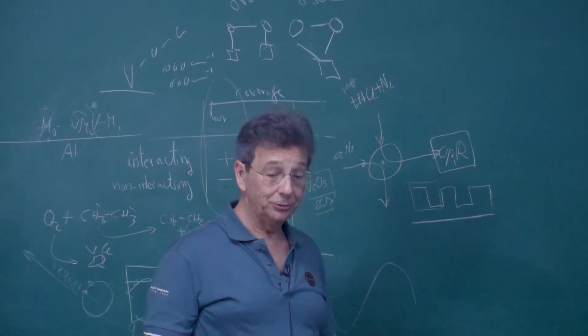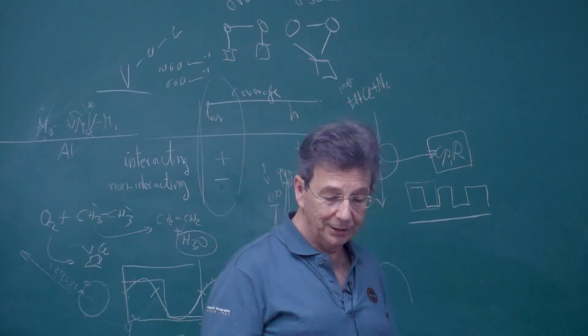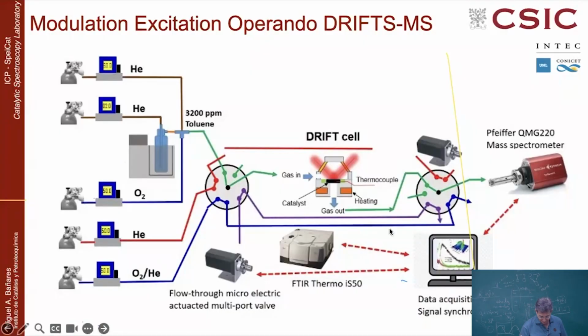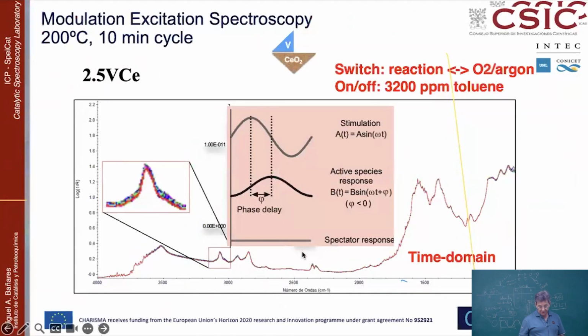Well, you have to find out. It depends on how the system is responding, but basically this is what it is. So you use these kinds of automatic valves where you establish the frequency and you do that. And you can do it with an infrared cell, a Raman cell, or whatever, and monitor what is happening. You measure online with mass spectrometry, and you measure the activity, and you measure with the spectrometer what is happening on the sample. And this is what we get.